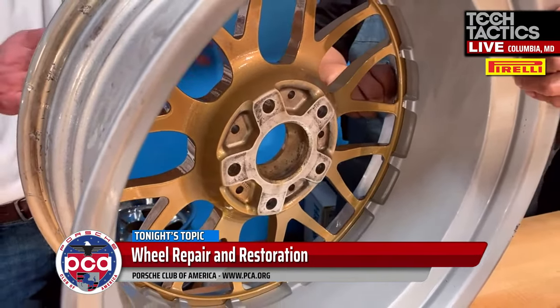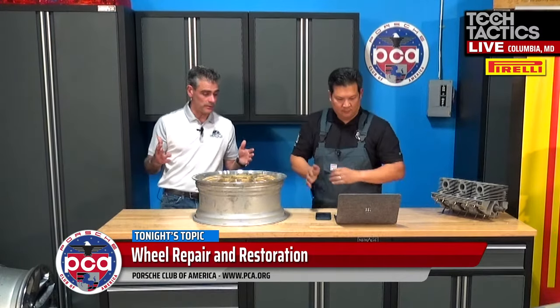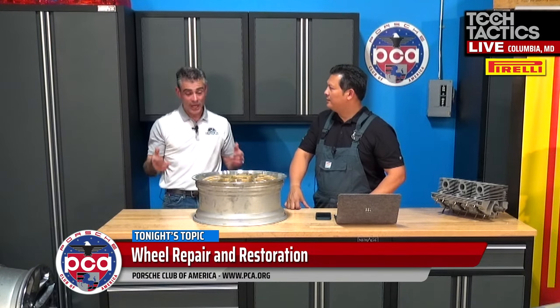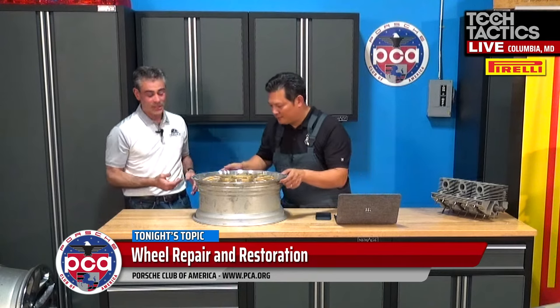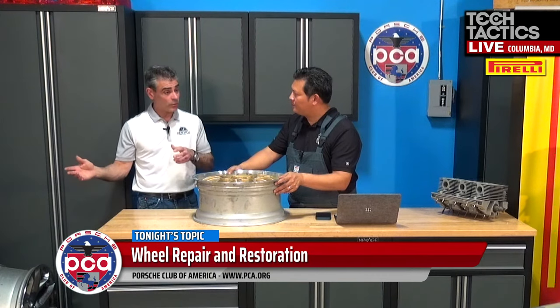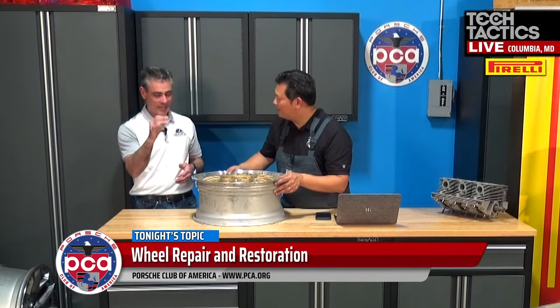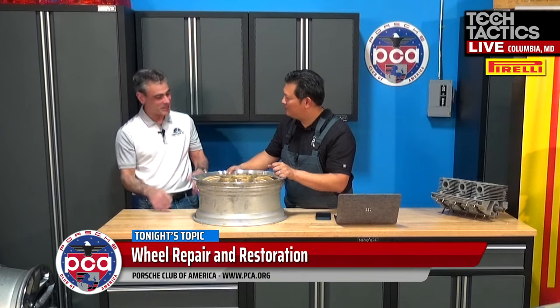And that's the other thing we do — especially with a two-piece or three-piece wheel — once the wheel is done, we spin them all on the balancer. We take the hood off and watch the wheel spin. If you see it spinning perfectly straight, you put it together. I had a three-piece wheel today where one of my guys said he put it together but it was spinning terribly. I asked 'did you check the back of the hub?' There was a big chunk of powder coat just sitting there — I took an almost-spackle knife, it fell off, and now it spun perfectly.